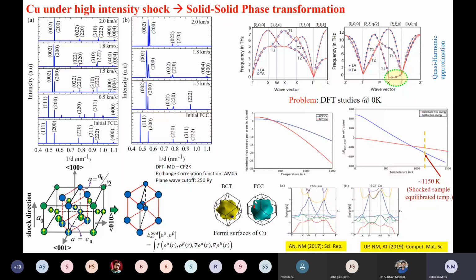Now, what we were seeing in here is that, interestingly enough, this is actually a first find, we should say, in which we observed that copper under very high intensity shock loading undergoes a solid-solid phase transformation. This was actually the first work in which we predicted that this is going to happen. We initially did it with some molecular simulations, and then in order to verify that, we also did some electronic contribution. We published this work sometime back, in 2017, 19, around that.